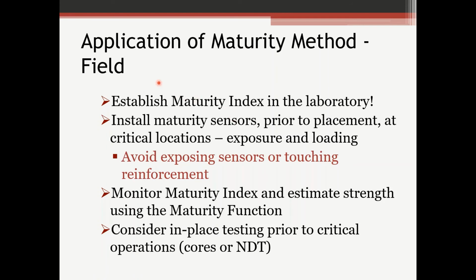So after we do that in the lab, we can install the maturity sensors in piers, footings, bridge abutments, whatever, maybe at some critical loading locations. You want to avoid touching the sensors to reinforcement. You can tie them to the reinforcement, but just don't have them physically touching it. Usually the sensor itself is not touching the reinforcement, and then you just monitor the maturity index for strength gain, figure out what your maturity value is, go to the plot and figure out what your estimated strength is.